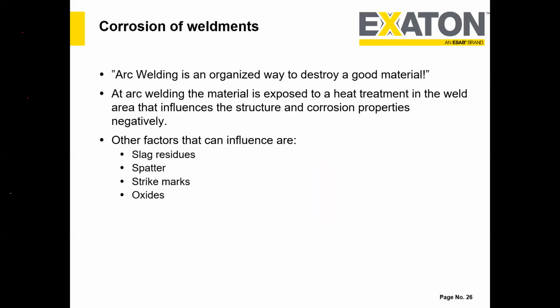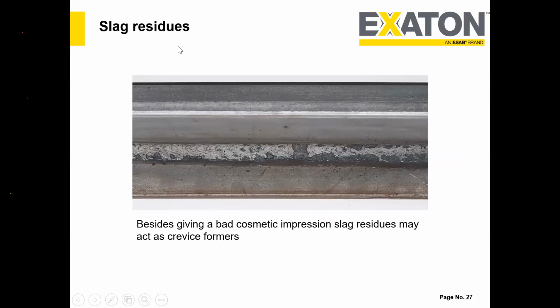Okay, so I will explain this one. There are a few corrosion issues in weld metal. I think the next slides will be much easier. So you see here the slag residues. Besides giving a bad cosmetic appearance, a slag residue may act as a crevice former. So please make sure that when you do the welding, you should not keep any kind of slag. It's really bad for corrosion. It has a high potential to create crevice corrosion.